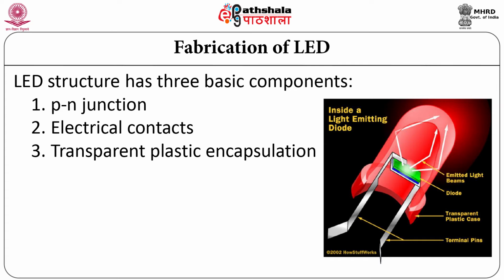Active films of the LED structure are normally grown epitaxially, often by liquid phase or vapor phase epitaxy. Common substrates used are compounds of gallium, arsenic and phosphorus. The PN junction can be created by either impurity diffusion, ion implantation, or it can be incorporated during the epitaxial growth phase.